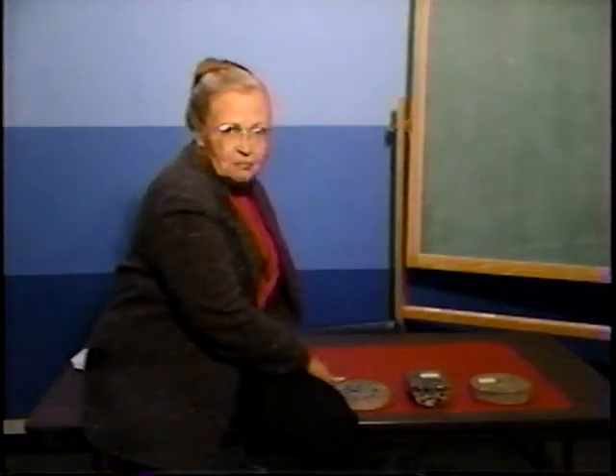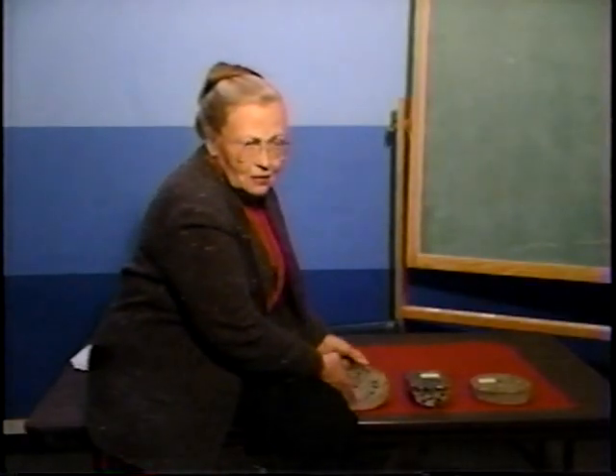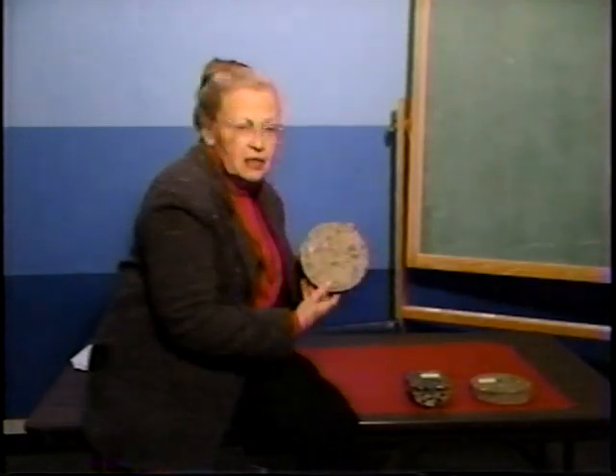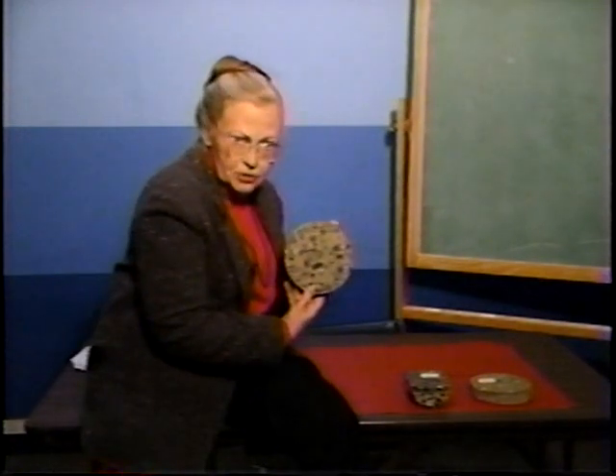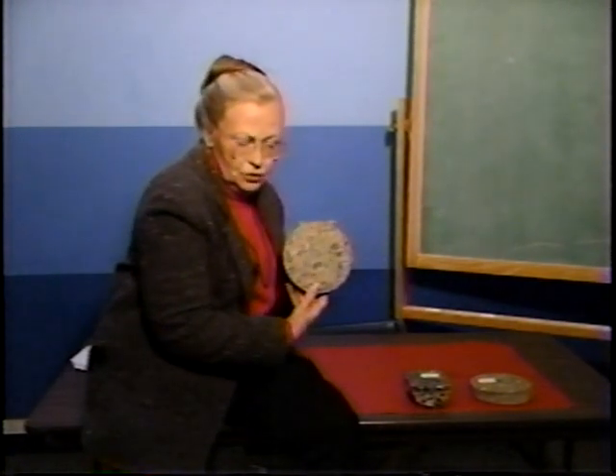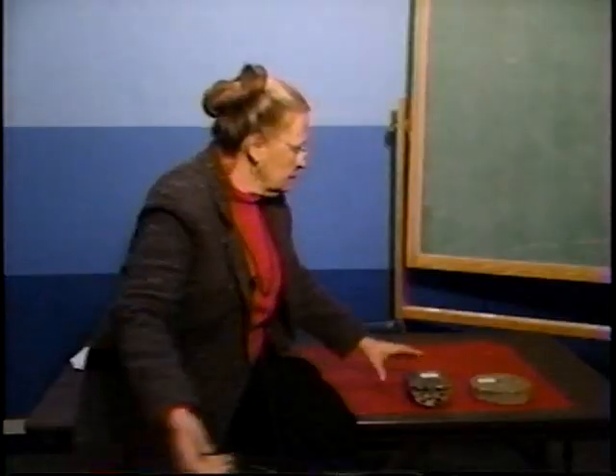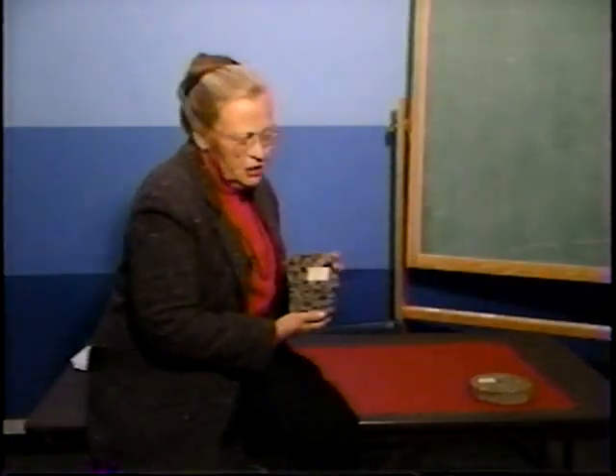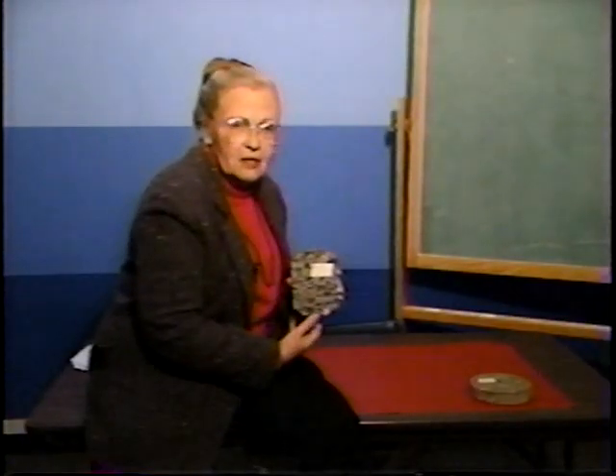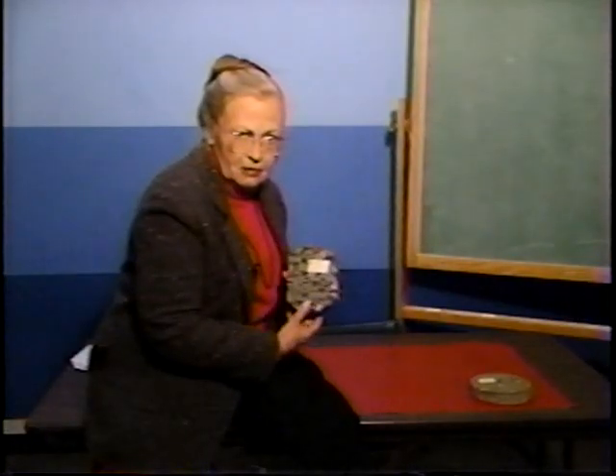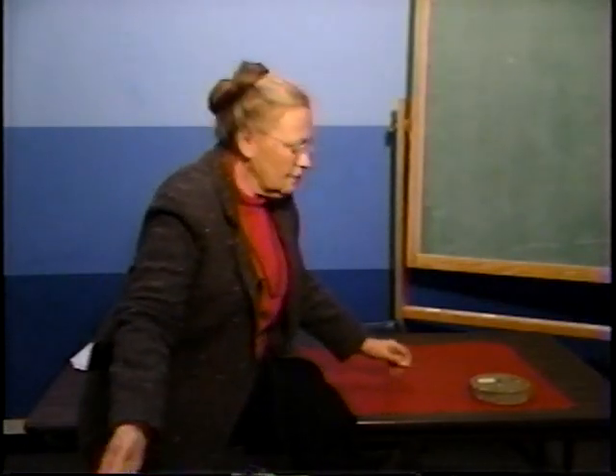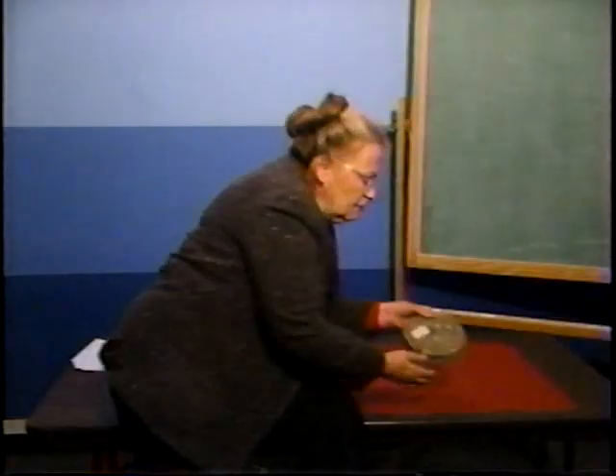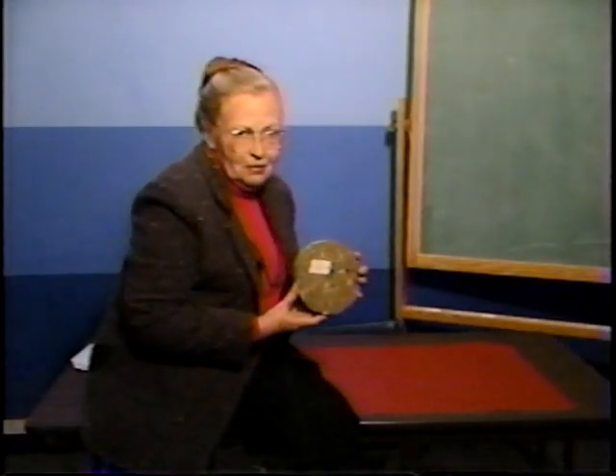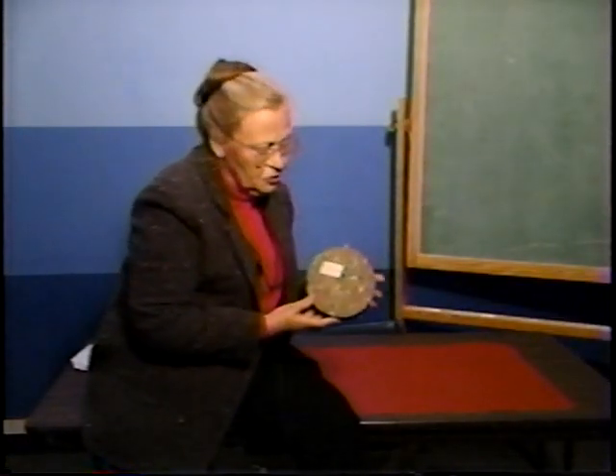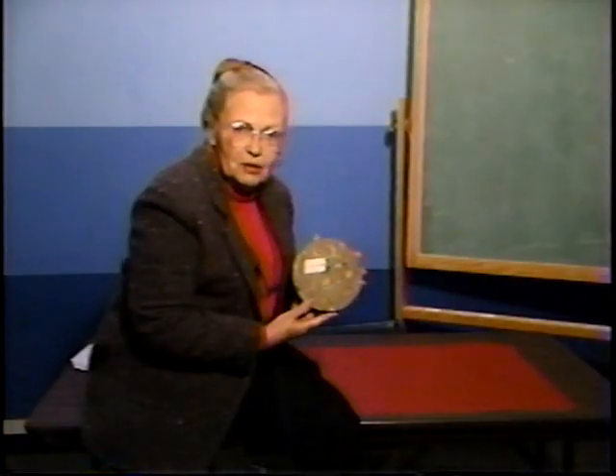I have here 3 specimens that are going to be passed among you with different percents of air. This one has only 1.5% air, way below the amount it should have. This specimen is within specifications. It has 5.6% air. On the other hand, this one, way out. It has been determined to have 17.3% air.